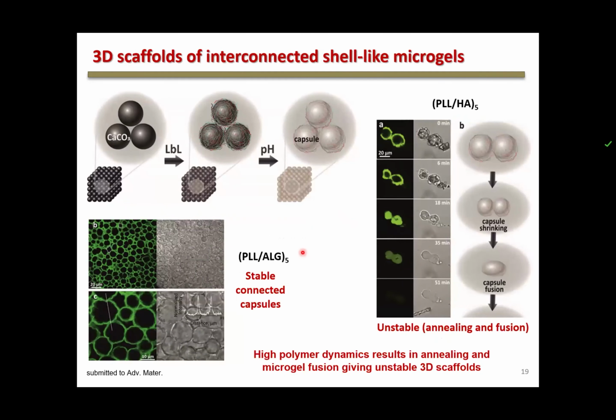So just to show you some ideas that one can pattern the surface not only in 2D but to make it in 3D. This is still unpublished, but I would like to share with you anyway because I found it quite exciting. So if you pack calcium carbonate particles not on the surface but in 3D, so just pack them in 3 dimensions like in a channel using microfluidics, for instance, then you can coat them in microfluidics as well, which is very easy with multilayers. And when you get rid of the calcium carbonate, you will have these capsules or microgels, you can call them differently depending on their structure, which interact from each other in 3D.